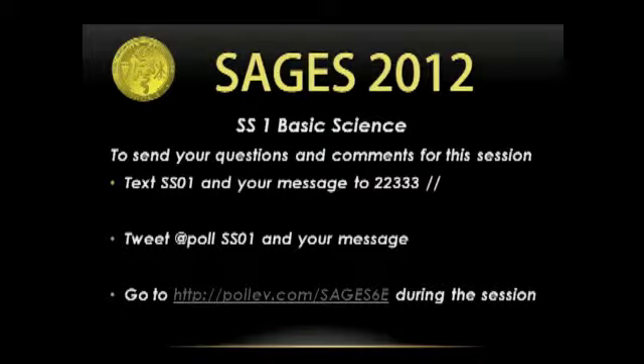My question is related to hiatal hernia repairs, and I don't know if it's okay to ask if you have a personal bias towards which product you use in particular to reinforce hiatal hernia repairs. It's interesting that Surgisis didn't show a lot of enzymatic degradation, because I found that in an infected environment, which is obviously different than hiatal hernia repairs, the Surgisis seems to dissolve pretty quickly and doesn't even seem to be there after a short period of time. We were using the Surgisis crural patch and have since gone away from it because we don't really think that it carries very good strength, and I've started to try to use the Gore-Tex product, which is a synthetic. I'm interested if you have any comment on that as well.